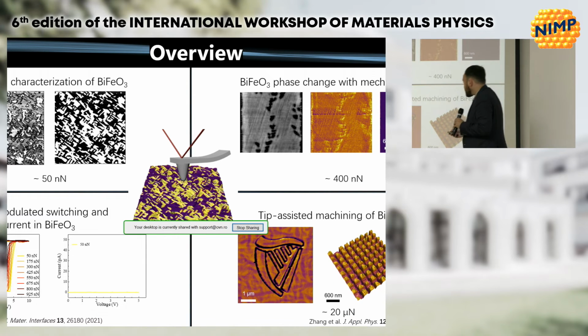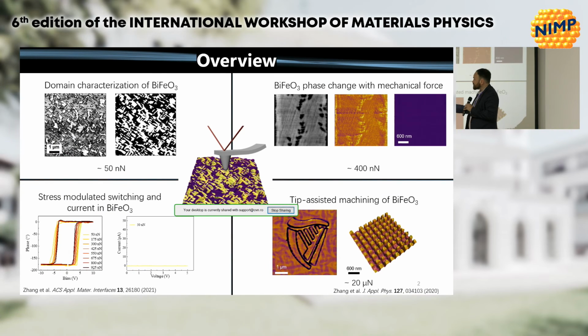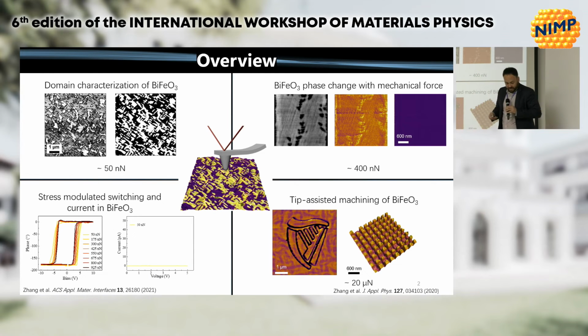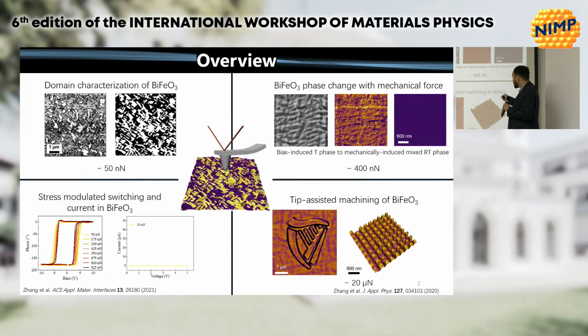Okay, so it should be familiar to most of us here that we can use, at relatively low forces, PFM, a scanning probe technique where you apply an AC voltage to a conducting cantilever and measure the converse piezoelectric effect, so the deformation of the film. We can do that at relatively low forces and get a nice map of the PFM amplitude and the PFM phase, where the amplitude shows how much the deformation was, and the phase is showing something about the orientation of the domains. In bismuth ferrite, if we go to a slightly higher force, we can introduce a structural phase change. So we can go from a bias-induced tetragonal phase to a mechanically induced mixed RT phase, so rhombohedral tetragonal phase. And this happens in this film at around 400 nanonewtons.